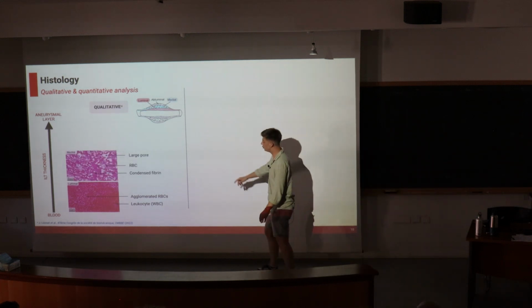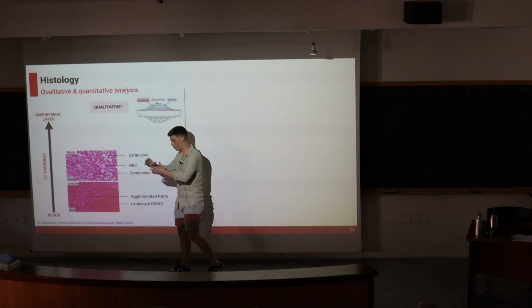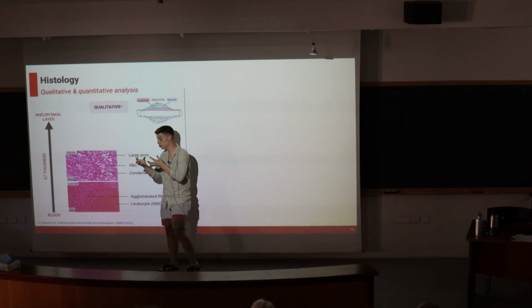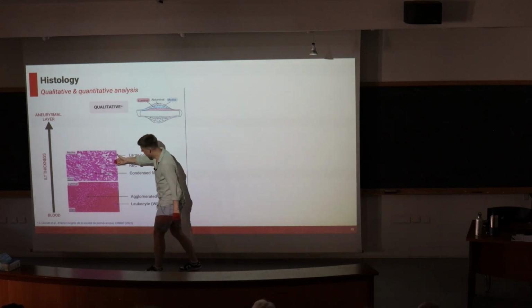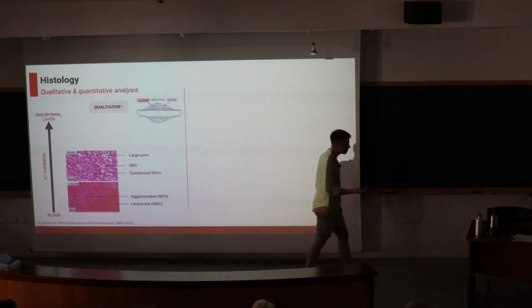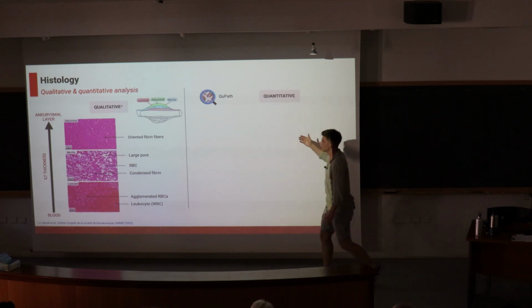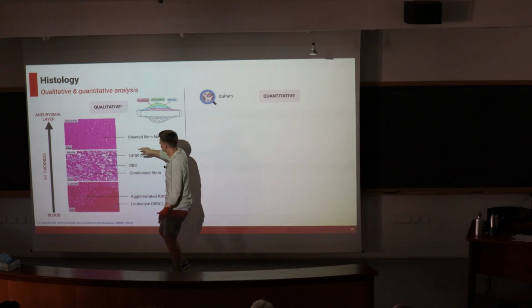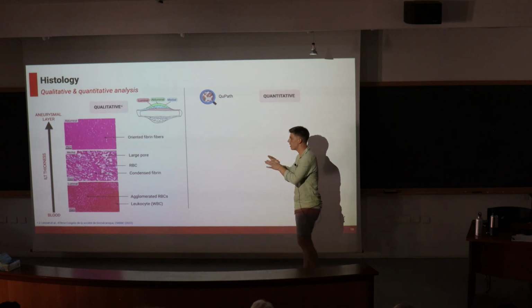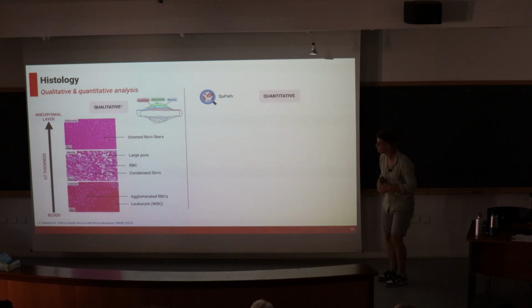If we move a little bit above to the next layer, the medial one, we can see that the structure is totally different. We now have a more condensed structure that creates larger pores, and in this specific layer we don't have cellular elements. And this is something interesting. If we move to the external layer, the structure is totally different again. We now only have oriented fibrin fibers like this, very condensed, without porosity. That is the reason why it's impossible to have perfusion.